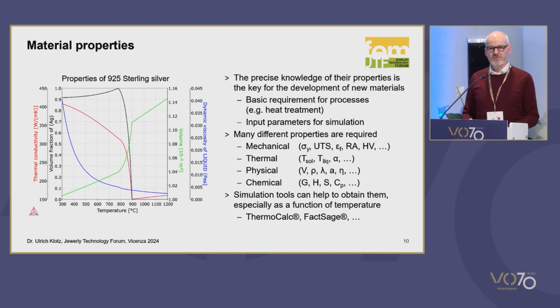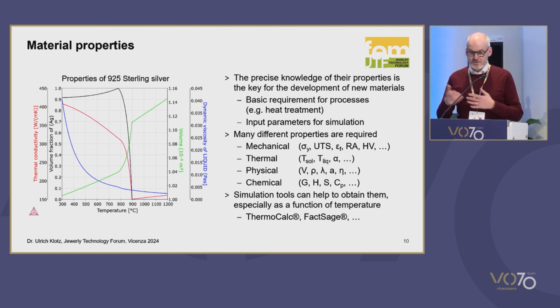They are quite easy to determine: tensile stress, elongation, hardness, reduction of area, and so on. Thermal properties, we are also aware: solidus, liquidus temperature, thermal expansion coefficient, and those properties are also not so complex to determine. But for the simulation tools, we need properties we are maybe not aware of, physical properties: the volume as a function of temperature in the solid and the liquid state, the density, the thermal conductivity, the thermal diffusivity,